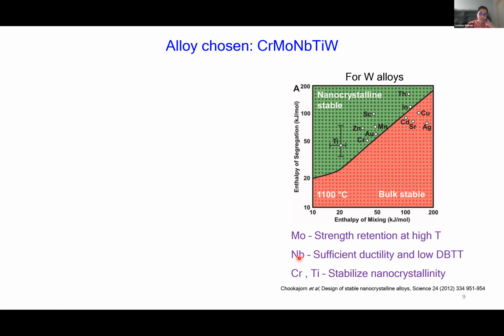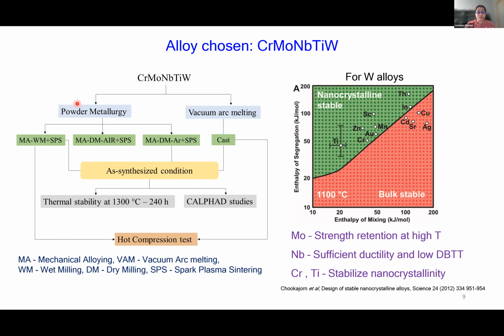And from our learnings from the literature, we have chosen niobium, which we need to have sufficient ductility, and also molybdenum and tungsten, which we need for high temperature strength. So this is why we came up with this composition. And this alloy we have tried to make through two different routes. One is vacuum arc melting, the conventional one, so that we can compare with the literature. Another, a non-equilibrium synthesis route, is powder metallurgy, wherein we use mechanical alloying.